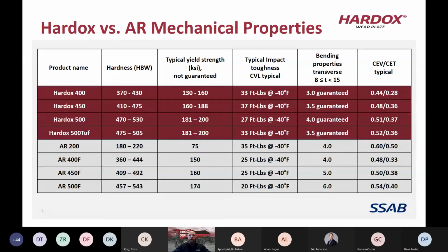One of the other good things about Hardox is our typical impact Charpy toughness values are generally much higher than what you find with standard AR plate. And our CEV values, carbon equivalent values, which give you a good indication of how weldable it is, are generally much lower than what you find with other generic AR plates. The CEV is basically a calculation based on the chemical elements in that steel, so the lower the CEV, the easier it usually is to weld.